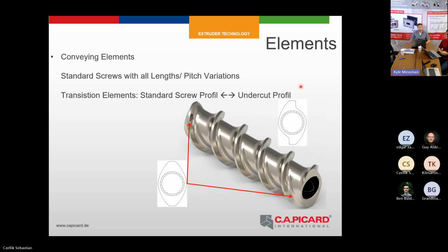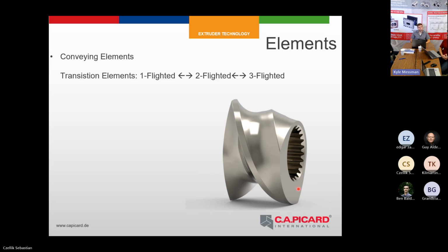So many customers don't want this, so we provide them with this transferring element, which has very good rheological geometry with no black spots or any other flow difficulties or reduced flow. One other transitional element we provide is where we transfer between different flights. Here, for example, we are transferring from a two-flighted element to a single-flighted element. The reason why we do this is the same as for the other element. We want to improve the rheological properties in the configuration.